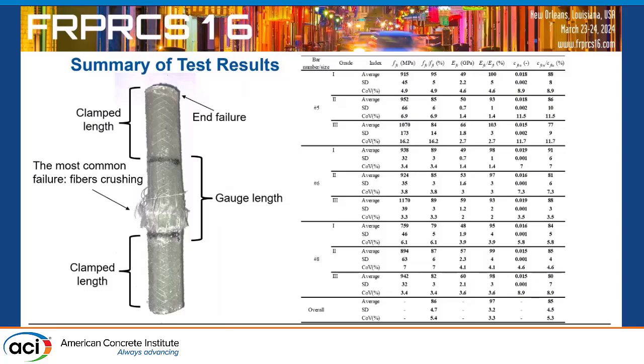One other thing is that the modulus of elasticity in compression over tension is 97%. So really, to me, modulus of elasticity in compression is the same as tension. So we should end this thing that it's over in guidelines and code. And in terms of tensile strength, 86%. But to be honest, we are not reaching that point at all. It's way after 0.003. Way after. I think that's almost there.